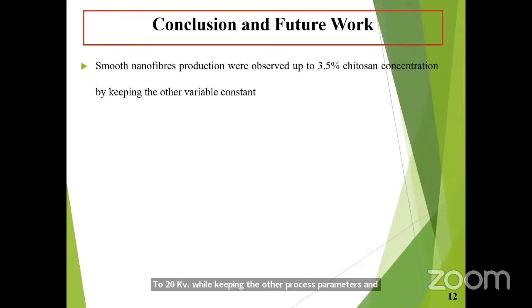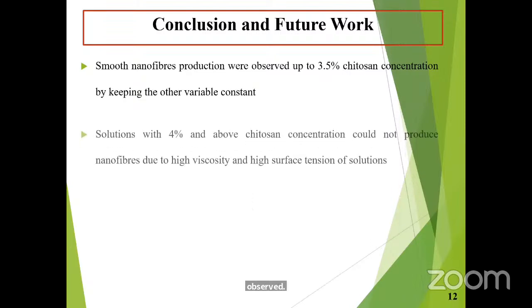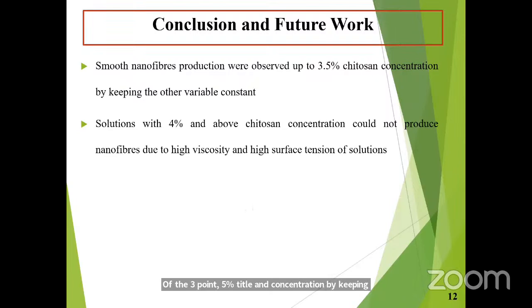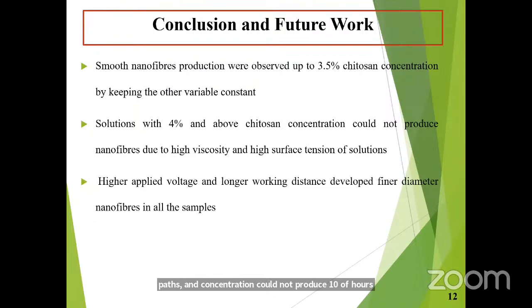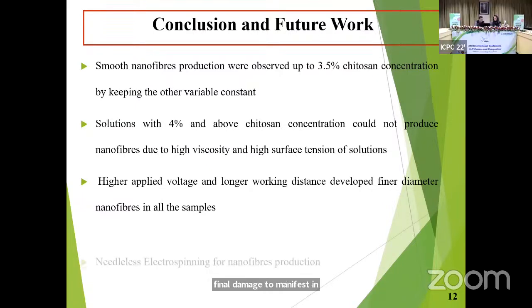In conclusion, smooth nanofiber production was observed up to 3.5% chitosan concentration by keeping the other variables constant. Solutions with 4% and above chitosan concentration could not produce nanofibers due to high viscosity and high surface tension of the solution. In terms of voltage and working distance, higher voltage and longer working distance develop finer diameter nanofibers in all the samples.